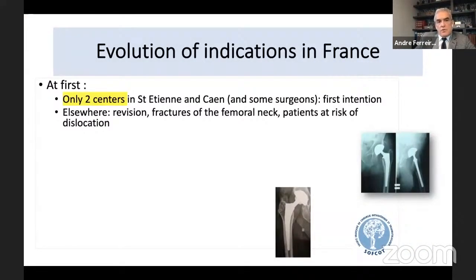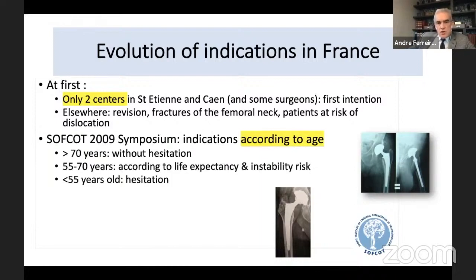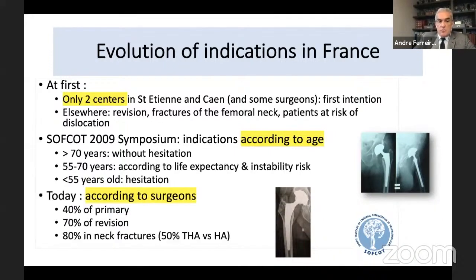So what was the evolution of dual mobility in France? At first, only 2 centers in Saint-Étienne and Caen used the first generation. And elsewhere, it was only for some cases of revision, fracture of the femoral neck, patients at risk of dislocation. And then, with the second generation, we use the age to indicate the dual mobility cup: after 70 years without any hesitation, between 55 and 70 years according to the life expectancy and instability risk, and before 55 years old, there was a hesitation. But now, today, it is according to the surgeons, and dual mobility cup is used in France in 40% of primary, 70% of revision, and 80% in cases of neck fracture.